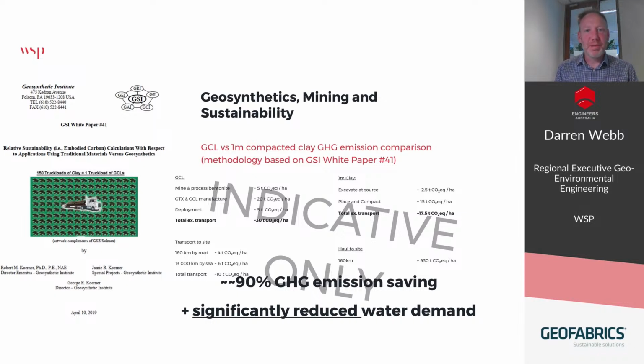there's a white paper that's been prepared by GSI, White Paper 41, which there's a screenshot of there, which outlines a methodology for assessing sustainability for traditional materials versus geosynthetics. I won't go through the numbers, but based on indicative calculations, and very indicative, it looks like there might have been in the order of a 90% or greater greenhouse gas emissions saving from using the GCL rather than a clay, and that's primarily driven by the haul distance for the clay. That's the main factor there.